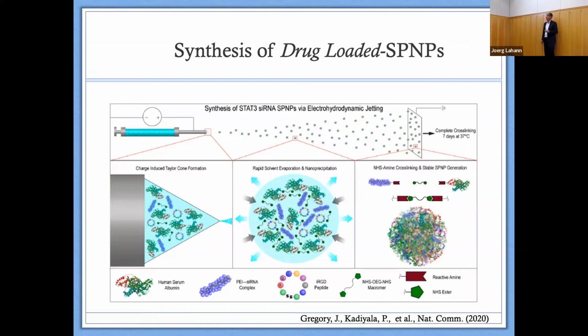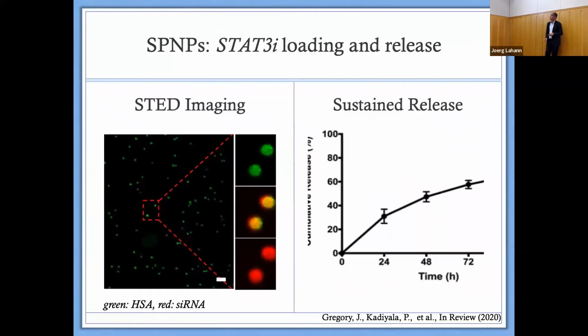And so basically, we complex that to a PEI to prevent it from diffusing too fast out. We also add a small peptide, iRGD, which is a transcytotic peptide. Ruoslahti has published on this a long time ago. And so we use this to basically induce transcytosis into the glioblastoma. That's the idea. We can show with ultra high resolution microscopy that we have a co-location of the protein, which we can easily fluorescently stain, and siRNA, which is also stained in red. So you see nice co-location, homogeneous distribution, and you get sustained release over a couple of days.